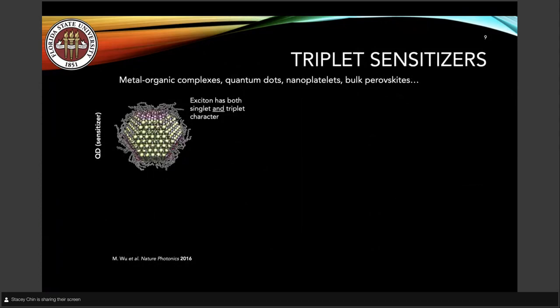And so what you do is you take advantage of triplet sensitizers. Initially people used metal organic complexes. Intersystem crossing, so the transition from a singlet to a triplet state, is enhanced in the presence of heavy metals. So if you take a metal organic complex, you can easily transition between the singlet and the triplet state.